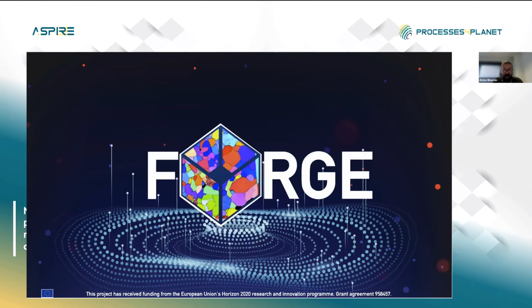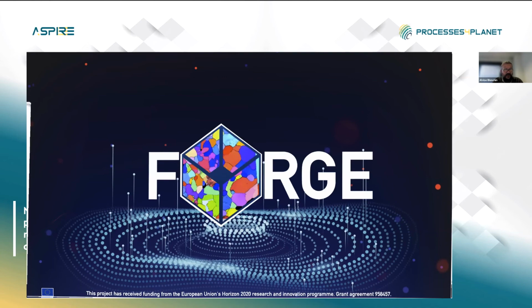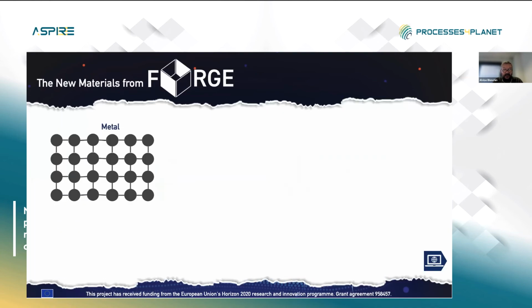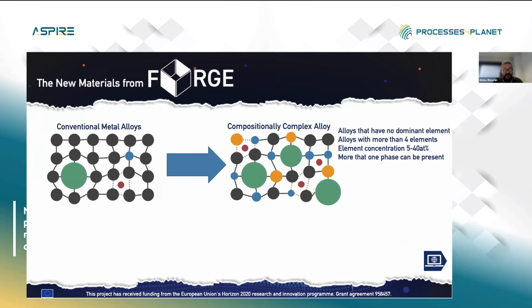It's a quite complex approach, and in Forge we are embracing these complexities because we are not looking into classic metals and conventional metal alloys, in which we have a primary element and then substitutional elements or interstitial elements. But we are looking into compositionally complex alloys that have a much broader definition. There are no dominant elements. More than 4 elements are present with concentrations from 5 to 40 atomic percent. And more than one phase can be present. This can give some benefits.